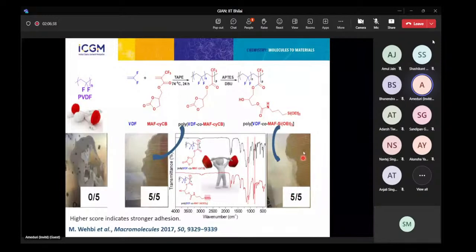But when you use PVDF, unfortunately, I mean, as expected, you don't have any groups enabling the adhesion, and so you have delamination of the coating. So whether you have cyclocarbonate or this system which undergoes some sol-gel reaction, you have been able to add very good adhesion, and this was also evidenced by the presence of silane by IR.